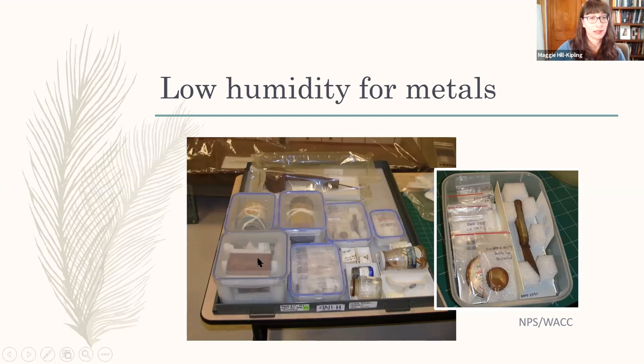We did notice that in certain situations, the silica gel was getting exhausted rather quickly in these boxes, whereas these Escal packages were holding their humidity low for a really long time. So anytime you're doing any of these microenvironments, it's important to really go back and look and see what you're actually maintaining. All of these have humidity indicator cards that you can view from the outside so that you know when your humidity has gone up, so that you can address it without having to open boxes and introduce humidity or whatever it is that you're trying to control, like with the oxygen.